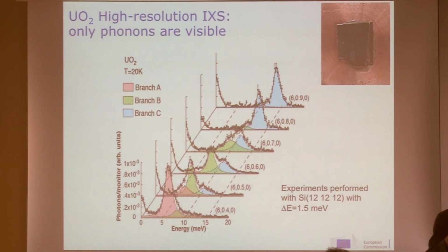You see only phonons. And actually, you observe uranium easily because we have 92 electrons. The intensity is proportional to Z squared. But you do not expect to observe the electric quadrupoles because these are due to only 2 electrons out of the 92 that are around the uranium atom.